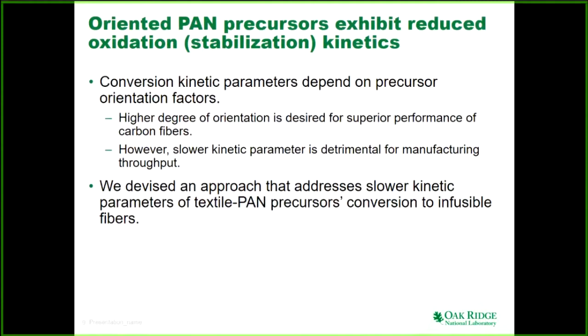Now, how shall I address that? I have to have a good conversion recipe for these precursors. A higher degree of orientation is really good for the performance of the carbon fibers, but slower kinetic parameters are detrimental for manufacturing throughput. Now imagine the technology that we developed earlier, where we tried to make textile-based carbon fiber at a high throughput rate. Whether it is textile PAN or specialty acrylic PAN, that is our baseline, the knowledge base we know, and all those methodologies would be applicable for this material too. No matter whether you have textile or specialty acrylic fiber, if you have a higher orientation factor, your kinetics will be slower. So how shall we address that?